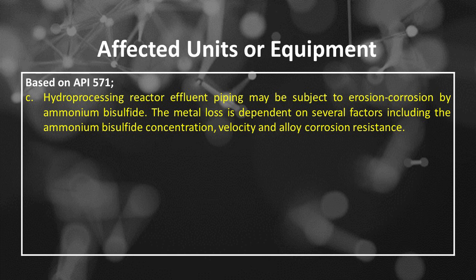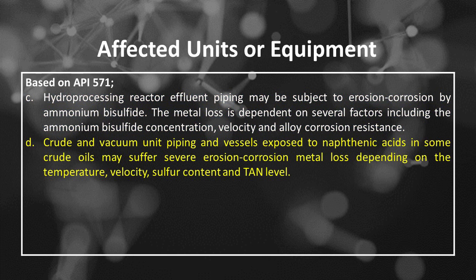The third is that hydroprocessing reactor effluent piping may be subject to erosion-corrosion by ammonium bisulfide. The metal loss is dependent on several factors including the ammonium bisulfide concentration, velocity, and alloy corrosion resistance. The fourth is that crude and vacuum unit piping and vessels exposed to naphthenic acids in some crude oils may suffer severe erosion-corrosion metal loss depending on the temperature, velocity, sulfur content and TAN level.